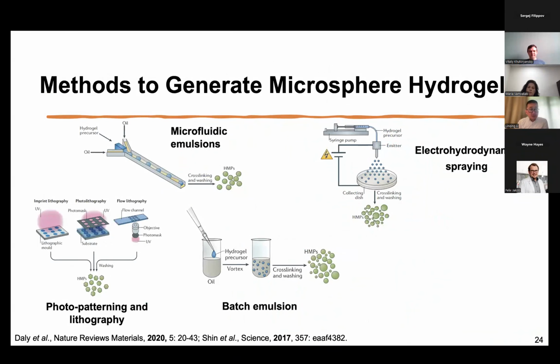The way that current literature generates these microsphere hydrogels is dominated by microfluidic systems. Both microfluidic systems and batch emulsion use the same concept: you mix the aqueous hydrogel precursor solution with the oil phase and vortex them, generating different particles. You isolate them, purify them, and anneal them to form these particles. The batch emulsion is really easy. It's a quick and dirty experiment, but you do suffer from heterogeneity in particle sizes.